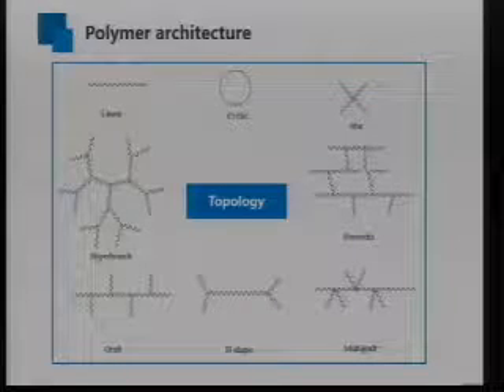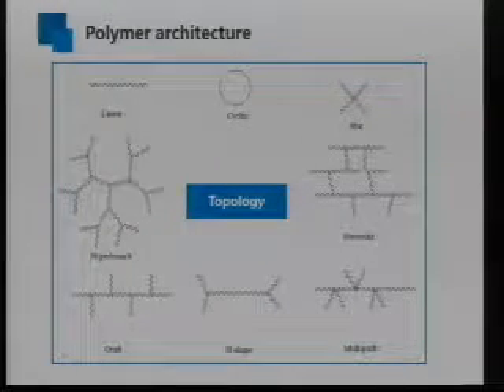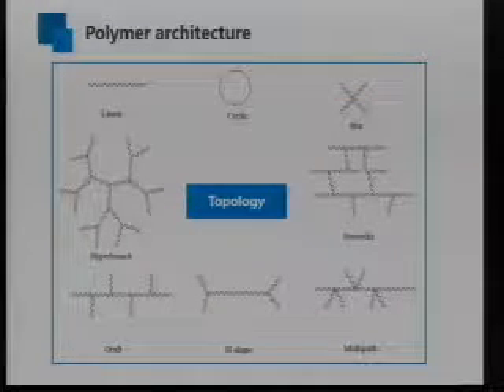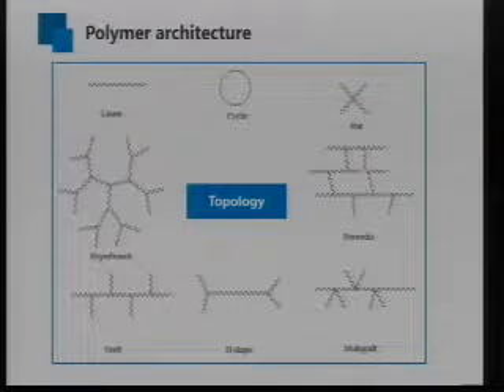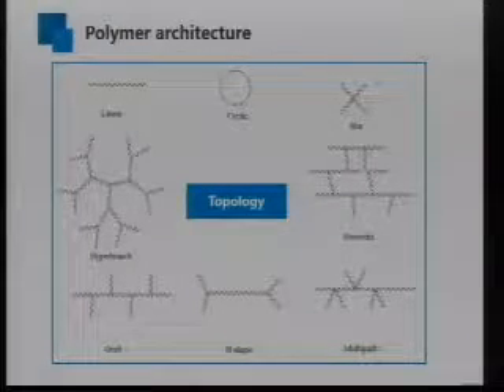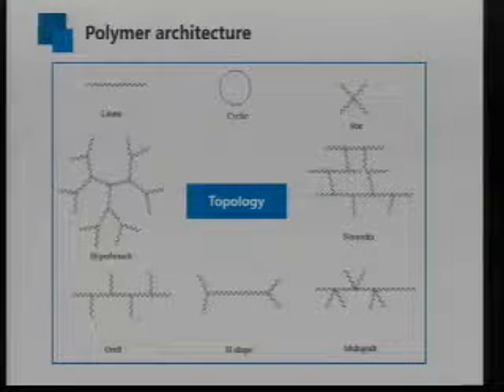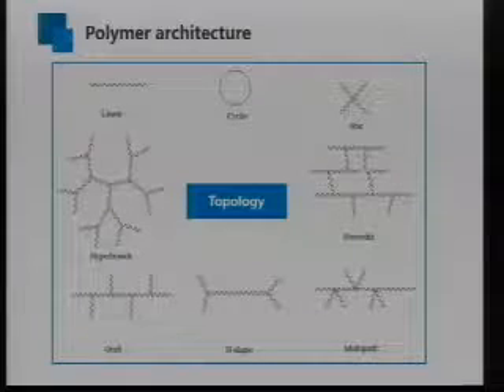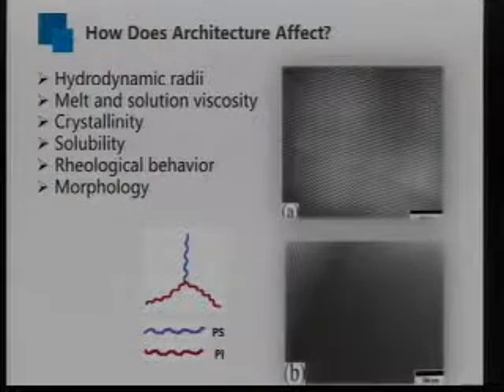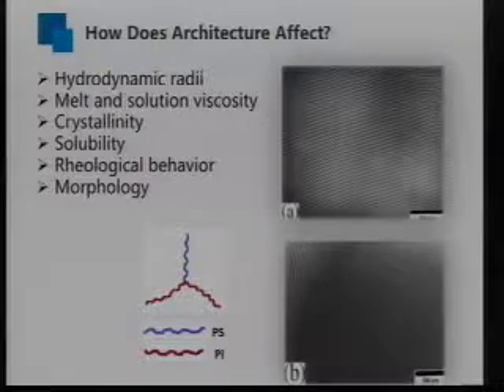So our strategy is to design complex polymer architectures. Different kinds of polymer architectures have been studied and developed, including linear block polymers, cyclic block polymers, polymer stars, hyperbranched polymers, polymer networks, graft copolymers and multigraft polymers, and H-shaped block polymers. As compared to linear block polymers, polymers with complex architectures can give a much lower hydrodynamic radius. Also, they can give lower melt and solution viscosity, with improvement in crystallinity, solubility, and rheological behavior. Moreover, complex architectures also have a better ability to tune the morphology.